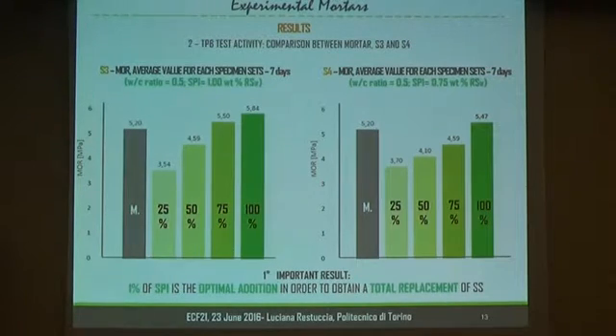While for the higher percentage of replacement of standard sand with recycled washed sand, we obtain an improvement in terms of modulus of rupture. In order to obtain a total replacement of standard sand, we found that probably the 1% of superplasticizer is the optimal addition. As you can see, in series 3, we obtain an improvement over the traditional mortar.